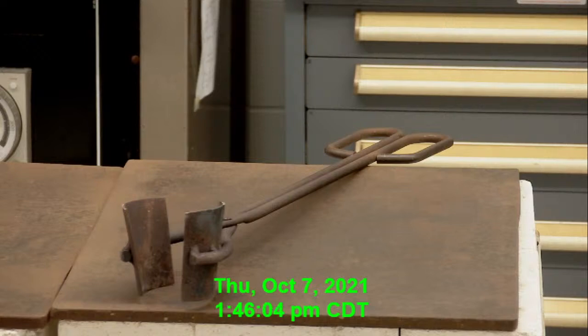Let's talk about the first batch. First batch we're calling L1. And so it is a white sand, sodium carbonate, calcium carbonate with a little bit of limestone, and 0.02 load of cobalt oxide. So that should be a fairly standard cobalt glass.